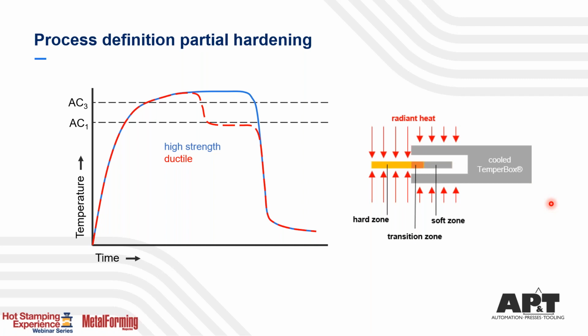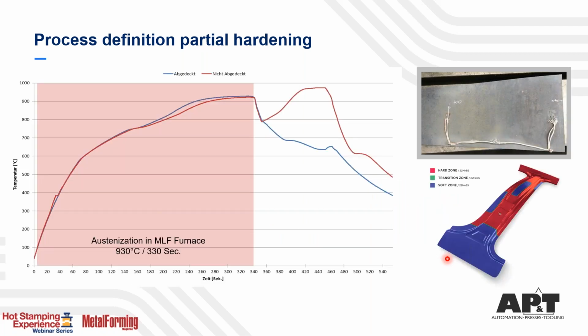What we achieve by blocking these areas from the radiation, you will see on the next slide, is a cooling effect which is similar to cooling the blank on air. This is what I brought you here. We have the austenitization. We mounted on a B-pillar, soft and hard zone, thermocouples. We measured the temperature increase during the heating. In the next section, we have the transfer out of the conventional austenitization chamber into the temper box. And in the temper box, we ramp up temperatures again in those areas that we would like to harden.